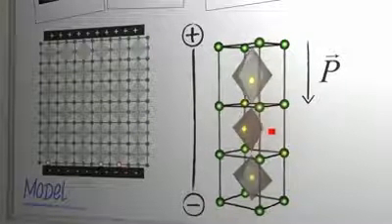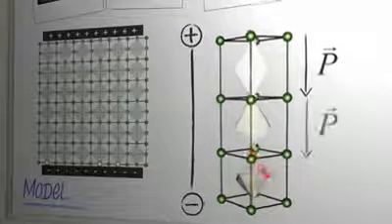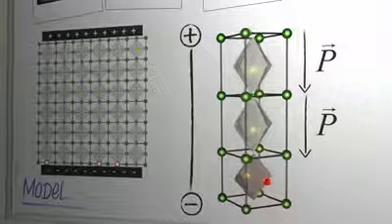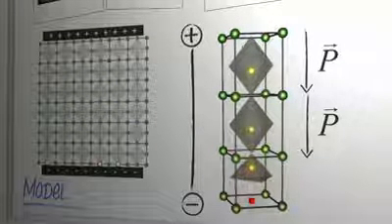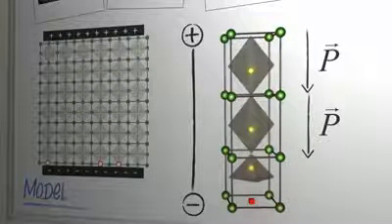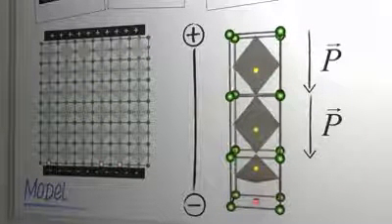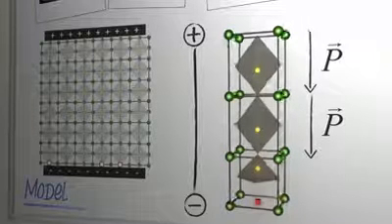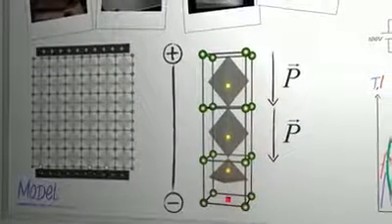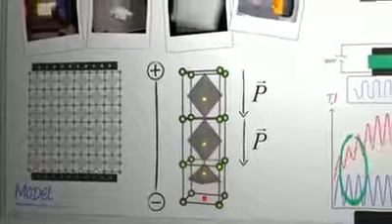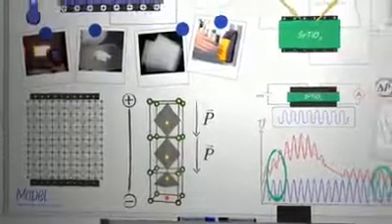Stretching of the unit cells now causes an inherent dipole moment due to the slight displacement of the titanium atom in the center of the octahedron, which is stabilized by the external electric field and remains stable even when the oxygen vacancy has left the unit cell. The temperature dependence of the dipole moments is responsible for the observed pyroelectricity. In summary, a dielectric to pyroelectric phase transition induced by defect migration with a pyroelectric coefficient of 30 microcoulomb per Kelvin and square meter was found.